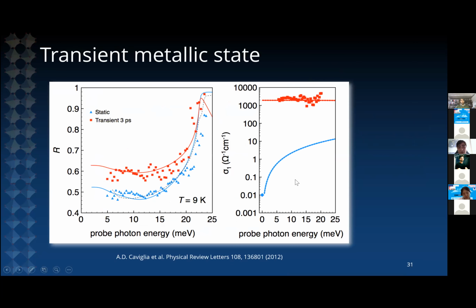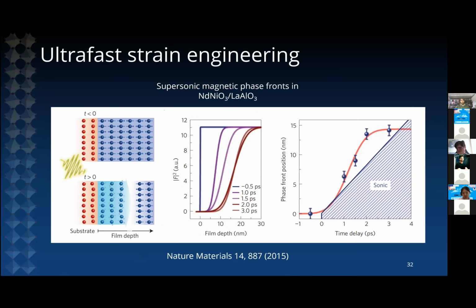So one first observation is that when you start from an insulating state, you can transform the system into a metallic state by exciting the substrate. So you have a variation of 5 orders of magnitude of the DC conductivity in the system driven by the excitation of the substrate. And in addition, when you excite the substrate, the antiferromagnetic order in the thin film is melted, and is melted in an inhomogeneous fashion.